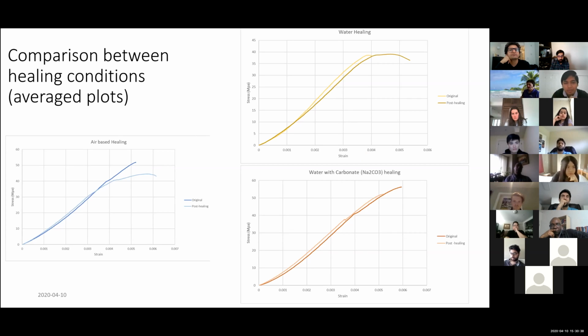And I can also observe the stress strain graph, though this is coming from the machine and not from the LVDT that I introduced. So we can see here that in terms of air-based healing, the original had a higher ultimate stress, and after damage and healing, the strength could not really recover up to that level. In terms of water, the strength was roughly the same, so there was a recovery of the ultimate stress in water after 90% of loading. And in terms of sodium carbonate, it performed slightly worse than the original value. So in terms of compressive strength, we cannot really say that one is performing better than the other.